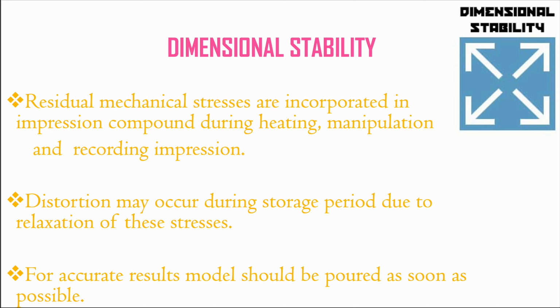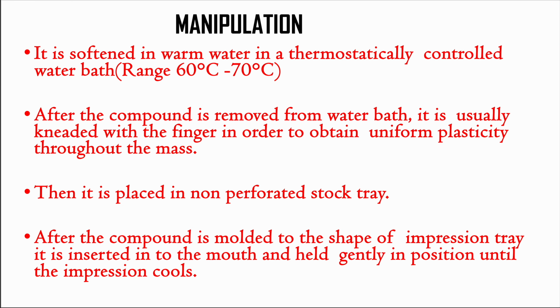Coming to the dimensional stability, residual mechanical stresses are incorporated in impression compound during heating, manipulation and recording impression. Distortion may occur during storage period due to relaxation of these stresses. For accurate results, models should be poured as soon as possible.